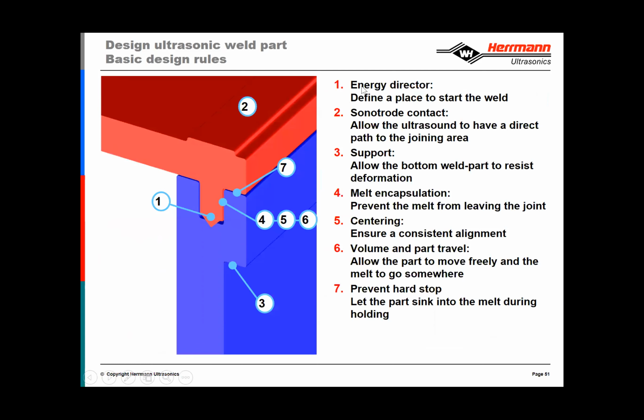So number 1 is having an energy director, defining a place to start the weld. So what we're talking about is a detail, and we call it a sacrificial bead. So this bead melts and flows and bonds, and hopefully will bond onto more than just the horizontal surface, that the volume of melt that's calculated will not just weld into the horizontal surface here, but will also bond onto the vertical surfaces. So that'll give you some mechanical advantages, as well as making the part leak free. Again, the name of the game is to reduce the surface area. So the intent of the energy director is that it be as sharp as possible, and that it minimize the surface area between the two parts to initiate the melt.